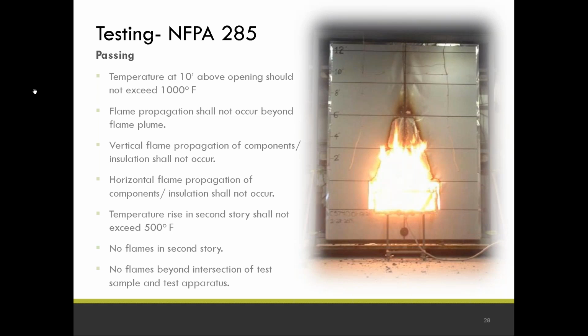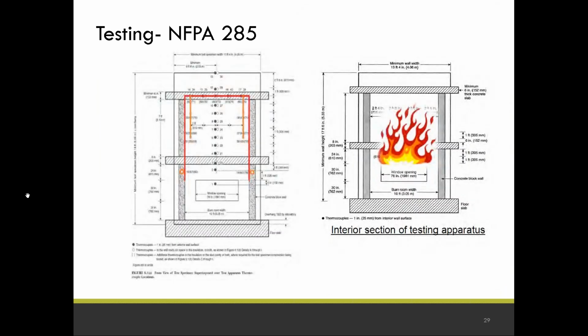You can't rise more than 500 degrees in the second floor. You can't have any flames in the second floor, and you can't have any flames beyond the intersection of the test sample and the test apparatus. In other words, they can't be spurting out the sides or the top. Again, the most common one that if you fail or is going to fail is the 1,000 degrees at thermocouple number 11, which is right in the middle of the wall.